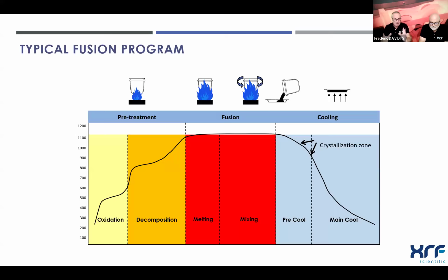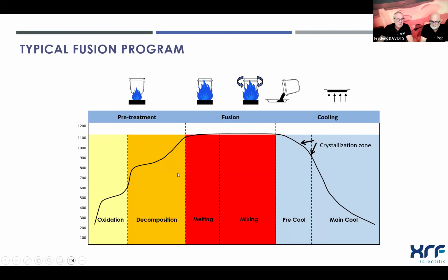Here we can see just a typical fusion program. The fusion devices of XRF Scientific can be calibrated, they can be defined just to your wishes. And of course, XRF Scientific does have the knowledge, so they already have some pre-defined programs. But in general, we have 3 main steps. It's the pre-treatment, which can consist of the oxidation and the decomposition part. Then we have the fusion, which is the actual melting and mixing of our sample with the flux and the other additives. And then we have the cooling phase.